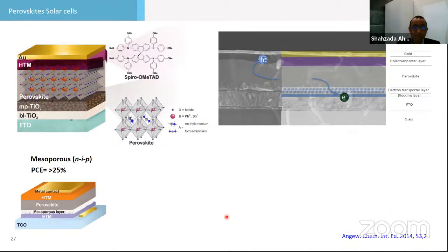If you look, this cartoon scheme shows the perovskite as the active material, sandwiched between a p-type layer and an n-type layer. We take commercial FTO or ITO glasses. We deposit an n-type layer, TiO2, to increase the surface area, or SnO2 now, or we can also use PCBM. We deposit a p-type material on top of it, and we finish the device with a metallic contact, which can be silver or gold of 60 to 80 nanometers. The thickness of the perovskite is 400 to 500 nanometers. So this is the cross-sectional diagram of an active device, and you will see that it exactly mimics the same structure.